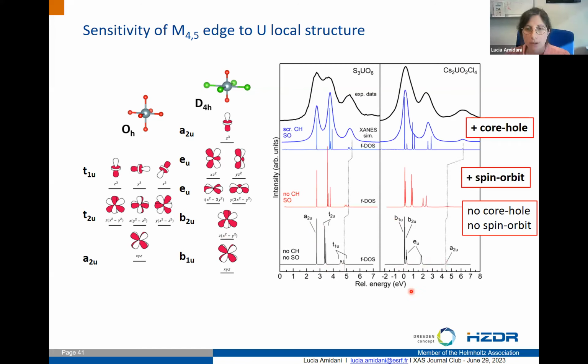Adding the spin orbit and, in the end, the core hole, increases the splitting of those main groups and brings the intensity closer to the experimental data.